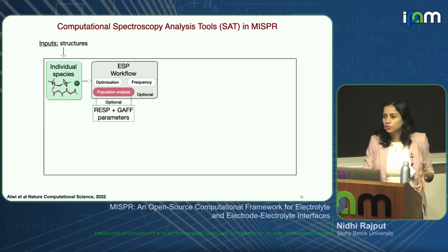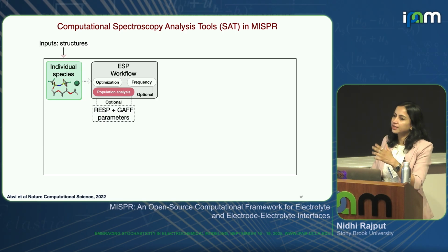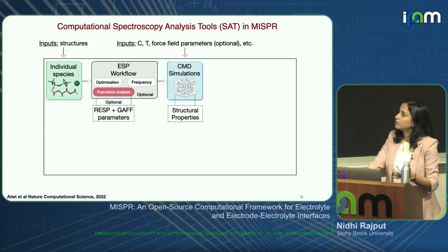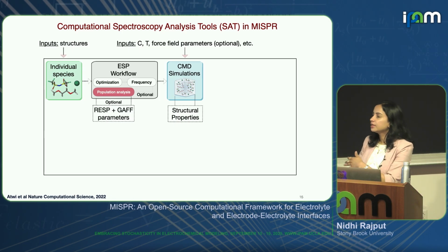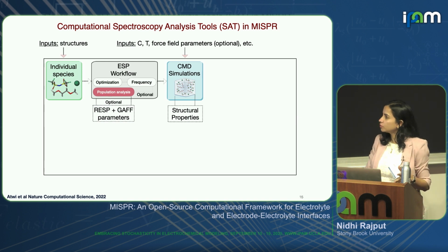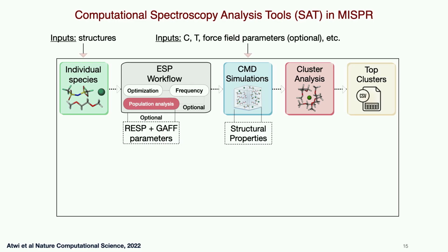It will run an ESP workflow, which will do all the DFT calculations, get the charges, and get the force field parameters. Currently, we have support for GAFF and OPLS, but the user can provide whatever force field parameters they want. It will then run the MD simulations, and here the user can supply the concentration, temperature, and their own force field parameters. Based on the structural analysis of the MD simulations, we then extract hundreds and thousands of molecular clusters and categorize them based on their solvation environment.